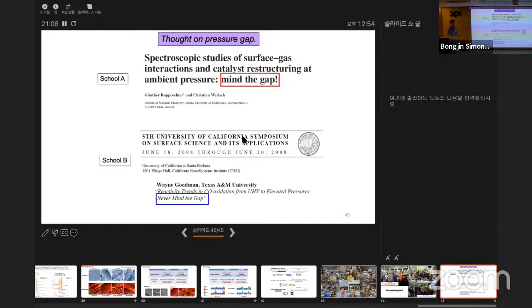That idea of CO2 dissociation was actually suggested by Hans-Joachim Freund. And we start to see similar things here too. I just saw this with oxygen on platinum 3 nickel. Underneath 10 to the minus 6 millitorr, I don't see change. I'll show it to you. We don't see changes. But at about 100 millitorr at room temperature, I start to see this being pulled to the surface.